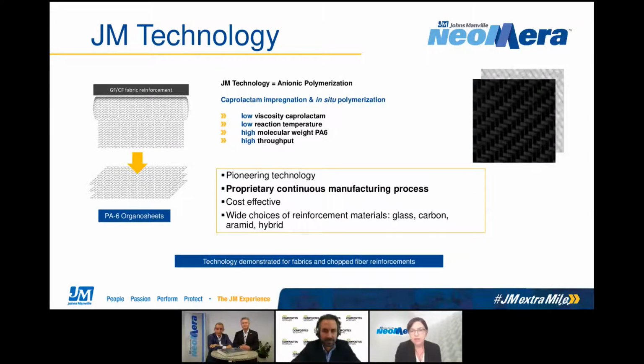So this is happening at a low reaction temperature, so below the melting point of the polymer. It's a very clean reaction. There are no byproducts, nothing that can evolve and generate voids during the process. And we obtain high molecular weight polyamide 6. It's a high throughput technology. And what's interesting and what makes it really suitable for high volume application is that because we're starting with this low viscosity monomer, we can impregnate very thick layers of fabric. So we reach up to 3,600 grams per square meter.